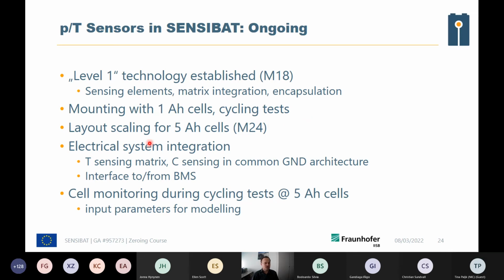At the moment, we're scaling this technology to 5 ampere hour cells, meaning we go from matrices containing 12 elements to 35 elements—a threefold increase in complexity. But since we already established this at level 1 technology, all the wiring requirements and crossing of lines are directly convertible into this 5 ampere hour cell layout, so this transformation should come without additional problems.